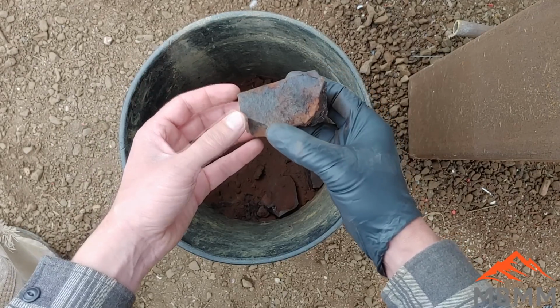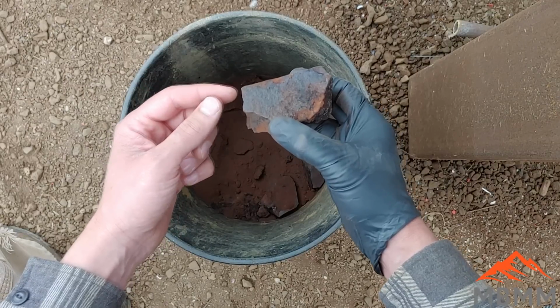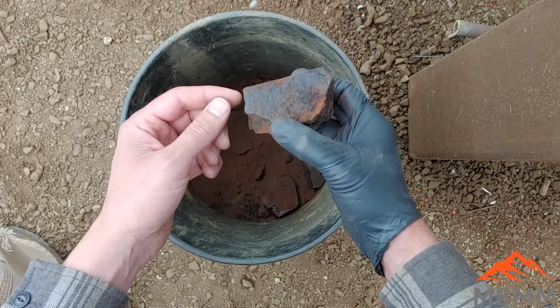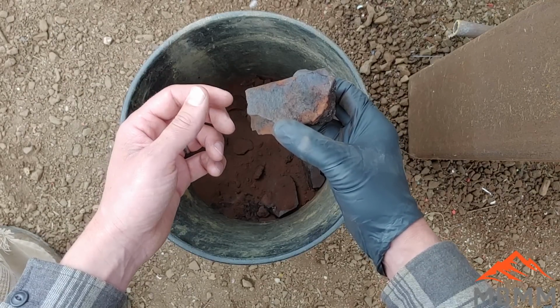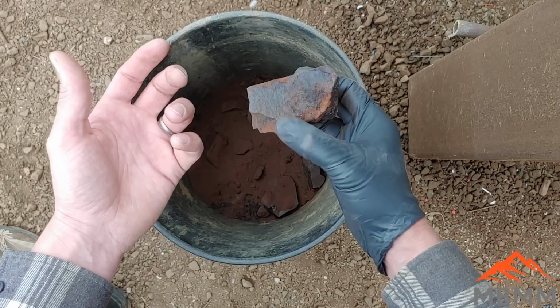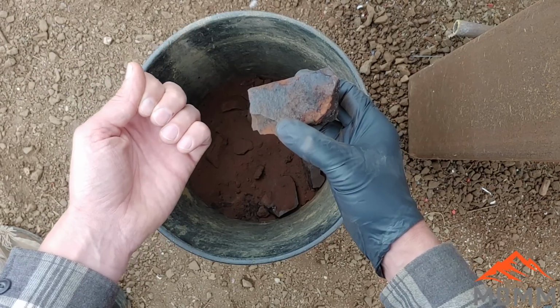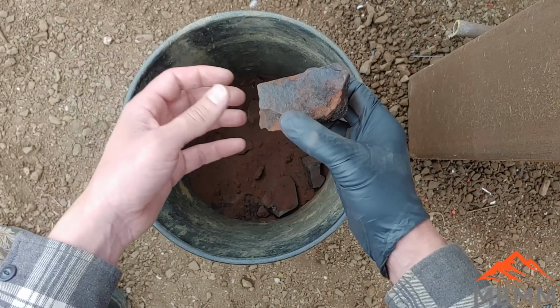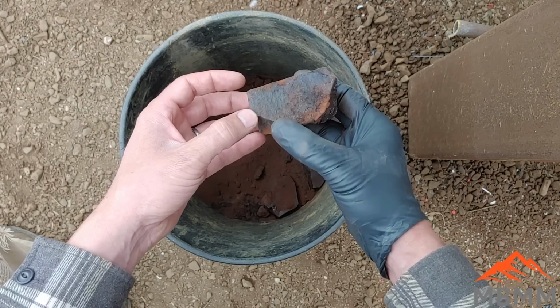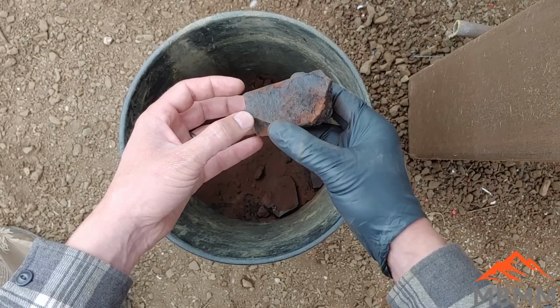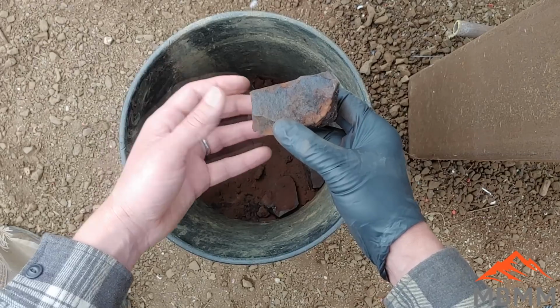The unique thing about FeS is if you make your slag very basic by adding soda ash or lye, the slag will dissolve that FeS. You can get rid of it by using the right chemistry in the slag and the flux. So those are kind of the three common ways to get rid of it.